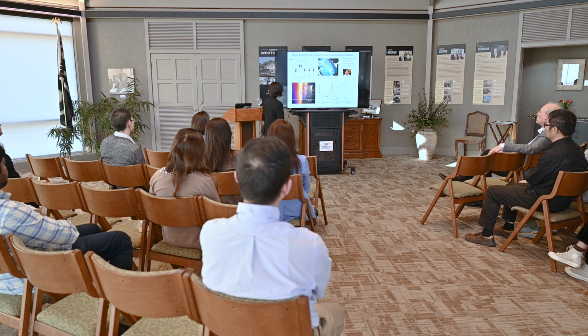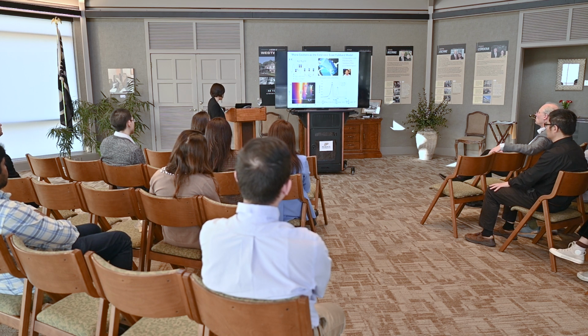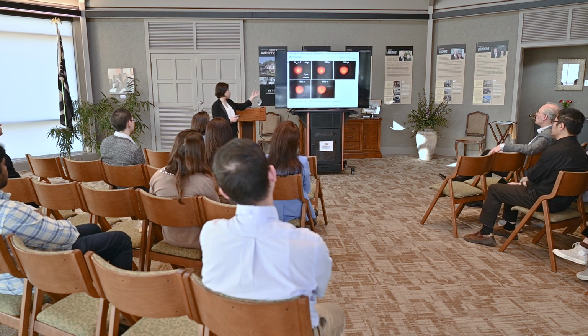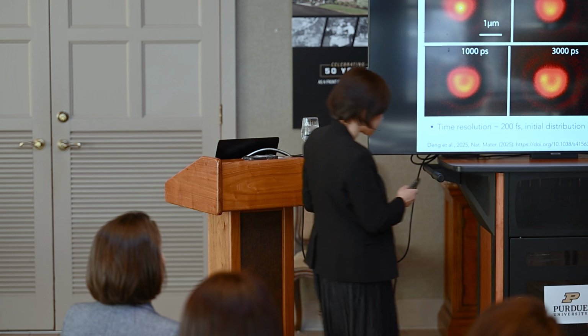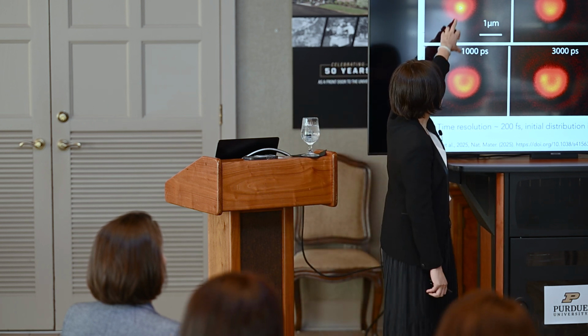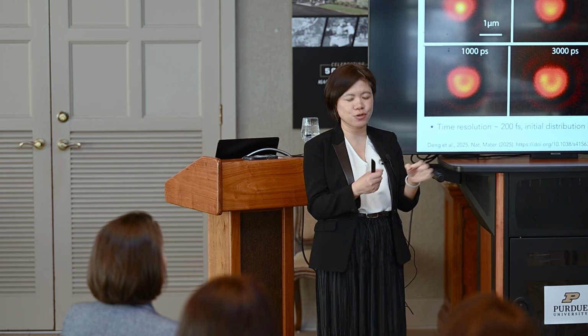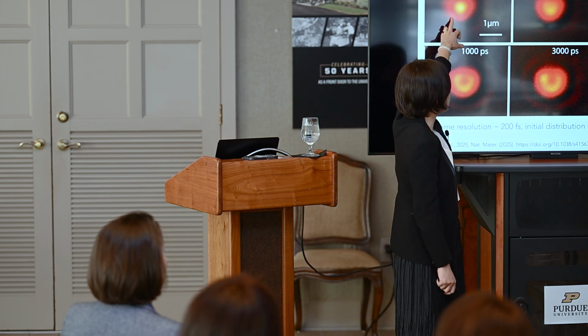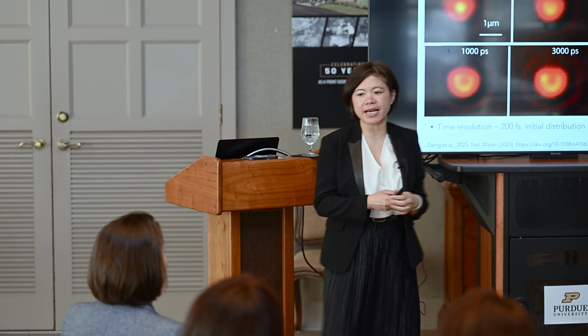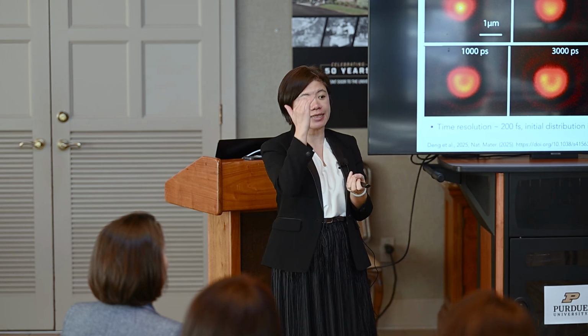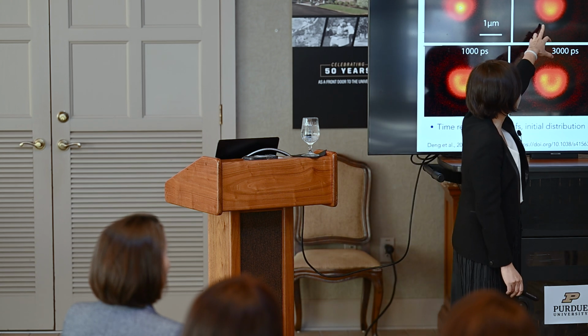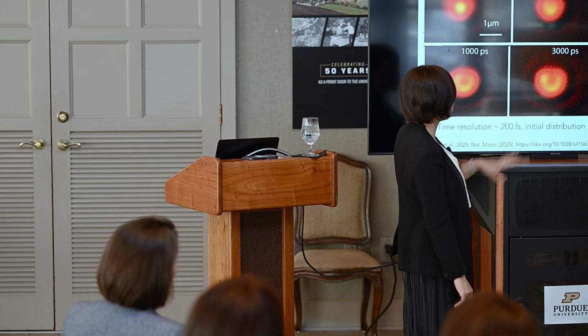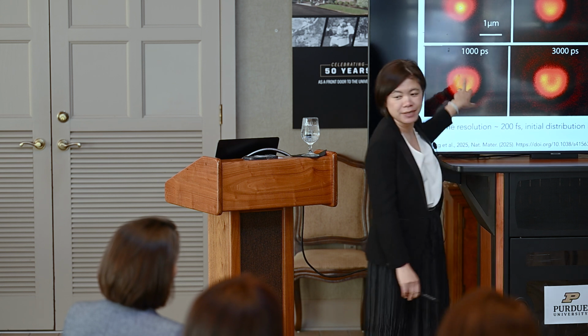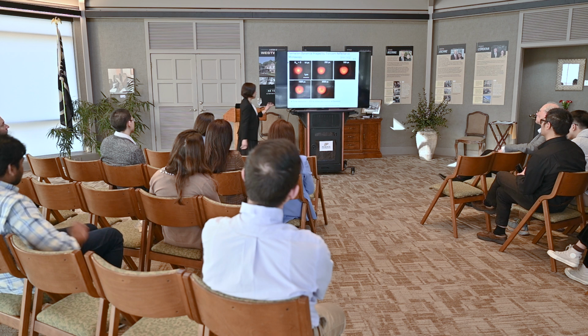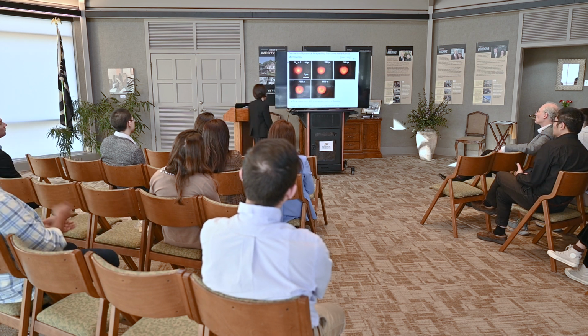And there's another interaction, this dipolar interaction I alluded to earlier, which also plays some role in this system. So now we can use our tool, like taking a movie of these excitons, right? Initially, in early time, we can see a big blob, which has to do with our laser beam. And this is how we generate the exciton. You can see initially the center is bright, because the center of our laser beam is the highest intensity. But then if you go to 200 picoseconds, and 500 picoseconds and so on, you can see the center actually becomes dim, and you have these ripple effects coming out.